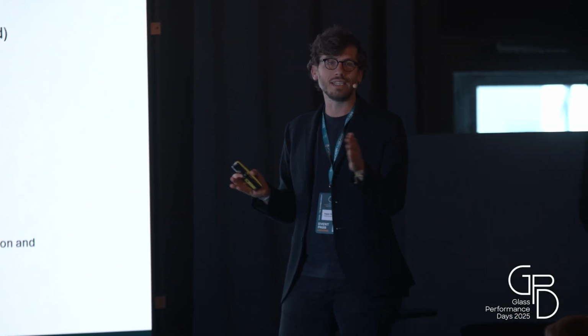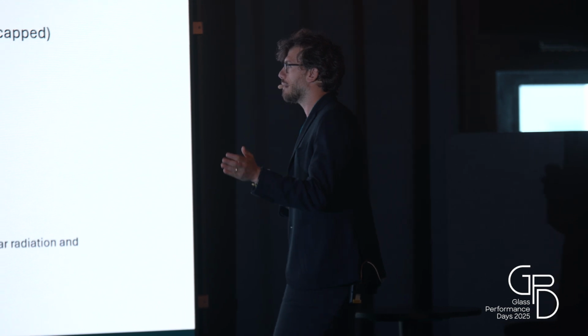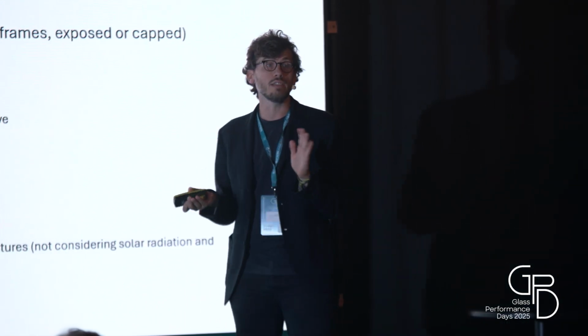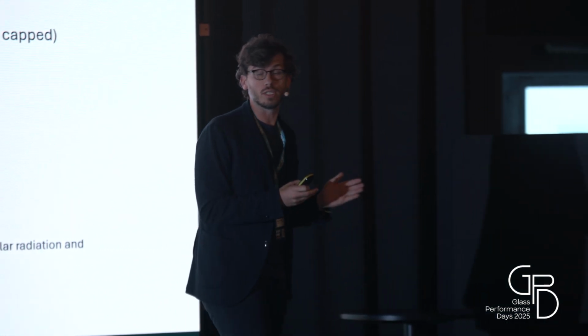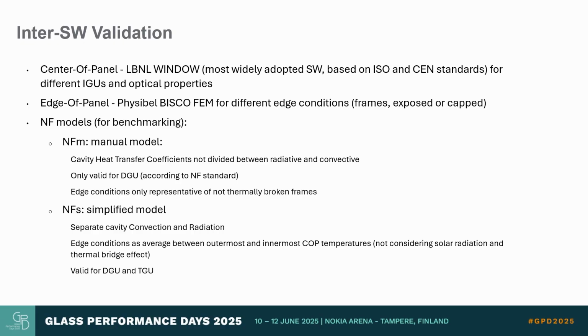That is not dividing the transfer coefficient between radiative and convective. It's only valid for double glazing units. You don't have a model for triple glazing units. And edge conditions are only representative of non-thermally broken frames, while the simplified one is more similar to what we use, but is also simplified in terms of edge condition.